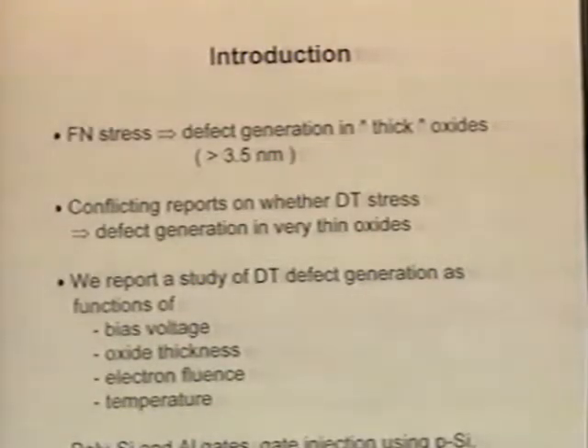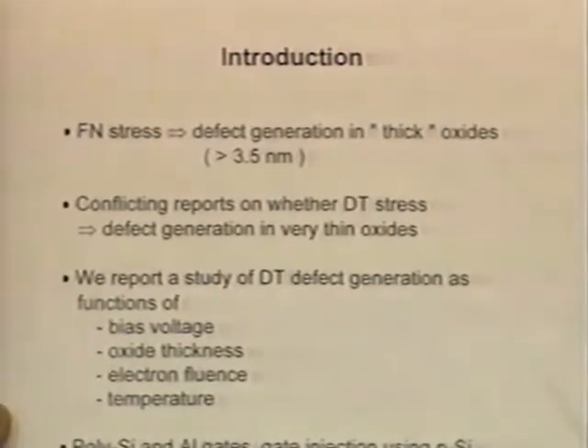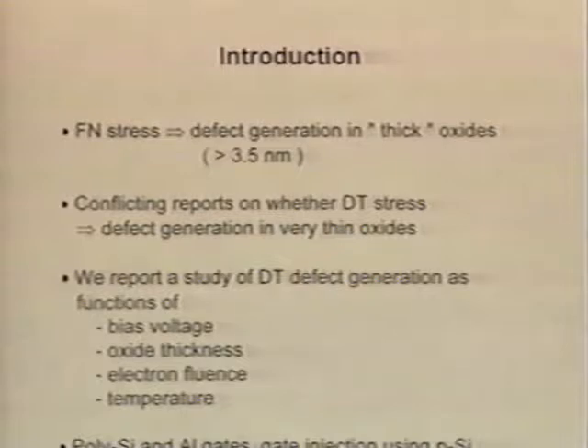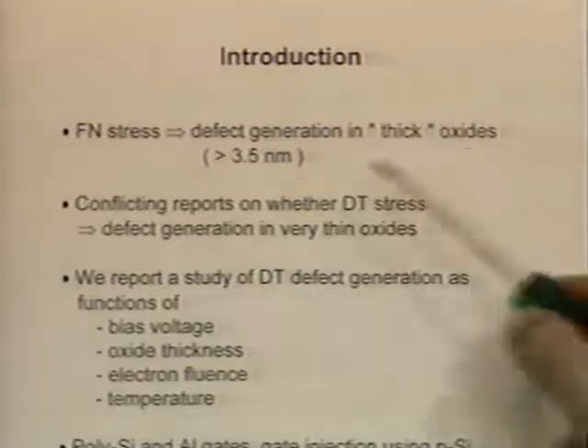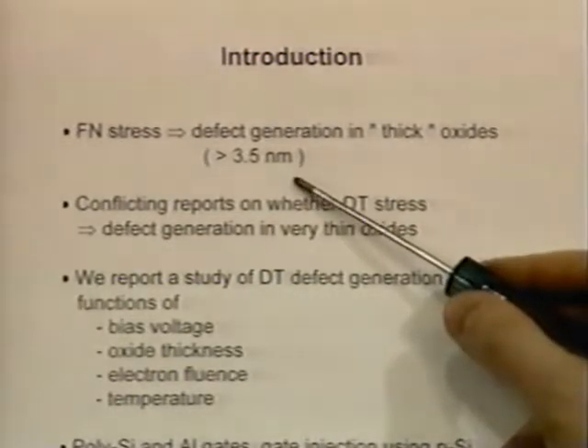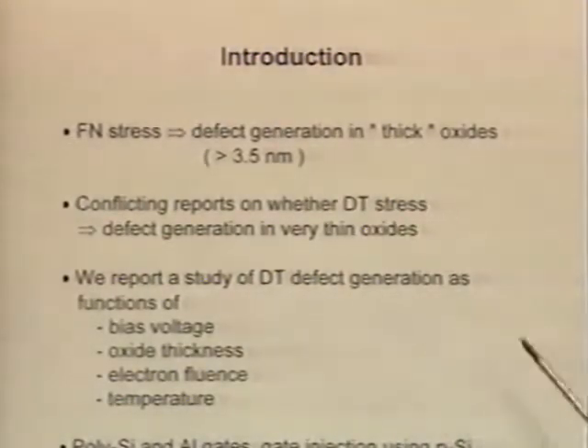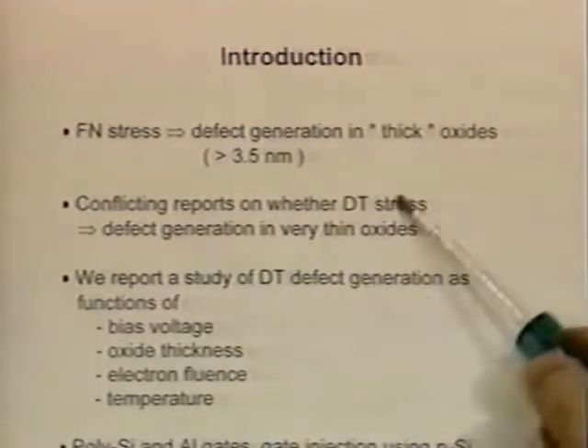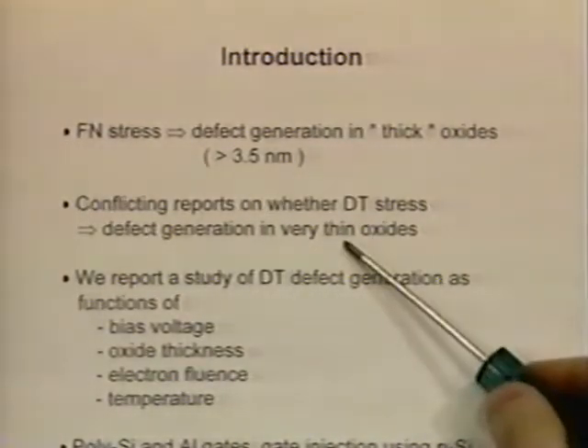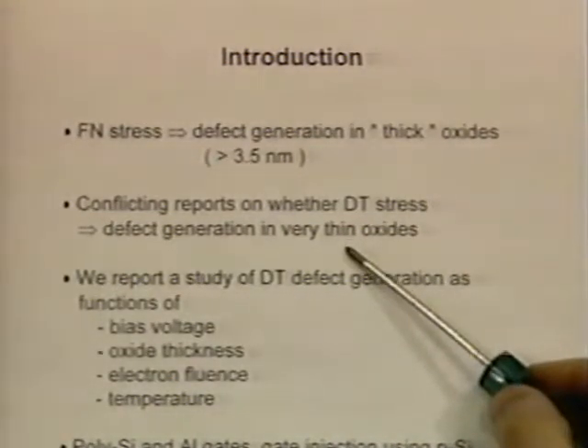Here's an introduction for the talk. There's a debate in the literature right now. The debate's between me and my collaborators. And that is, well, we know that Fowler-Nordheim stress leads to defect generation in thick oxides, and by thick I mean anything greater than 3.5 nanometers. But there are conflicting reports on whether direct tunnel stress really leads to defect generation or not.